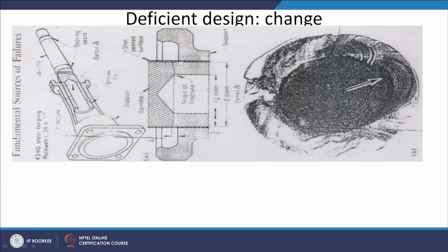This was the complete case where the spindle had a geometry with a change in cross-section. The bearing support area and the enlarged view of the root of the hole can be seen at this location. The hole was drilled too deep and reached the high stress areas where change in cross-section was taking place. This led to the nucleation of a crack at the periphery of this hole at the root, followed by nucleation and growth of the crack all around the periphery, causing fatigue fracture.